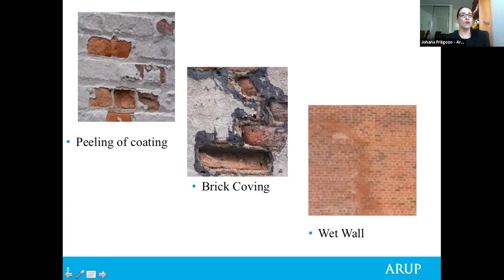We have brick coving, which is the cavity or hollowing of the brick. This is particularly common in areas where there is standing water or close to ground level, and it manifests in loss of material. Then we have wet walls, which usually manifest in water stains in some areas and other areas being dry. This is probably caused by dampness rising from foundations or problems with mechanical and plumbing systems.